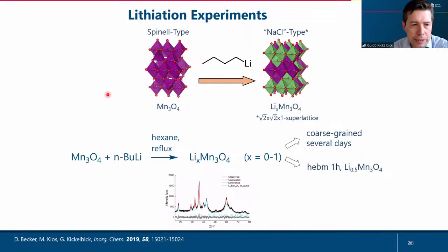But the question now again is, in the beginning, I told you that chemical reactivity should change. So the question is, how can we prove that chemical reactivity of a solid changes? One potential proof you have seen already before is lithium intercalation. So if you do an experiment without electrochemical intercalation, just by doing intercalation by a chemical approach, you have butyllithium and you take the manganese oxide and you put it in a suspension with n-butyllithium in hexane under reflux. Do we see a difference between the high temperature material which you get usually under usual solid state conditions, or the material which you get from the mill?